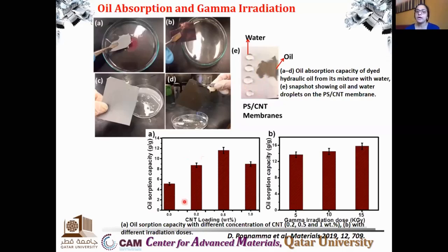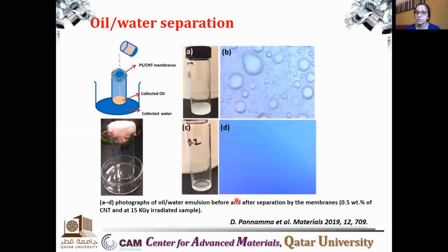And we also tested the oil sorption capacity with the different concentrations of carbon nanotubes and different irradiation doses. How we find out the oil sorption capacity is, we take a specific amount of the fiber, just dip it in oil, and find out the weight change after oil absorption. So this will give the gram per gram oil sorption capacity. And here also we got interesting results, or high performance, for the 0.5 weight percent of carbon nanotube.